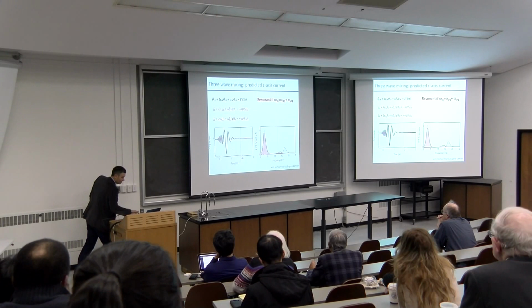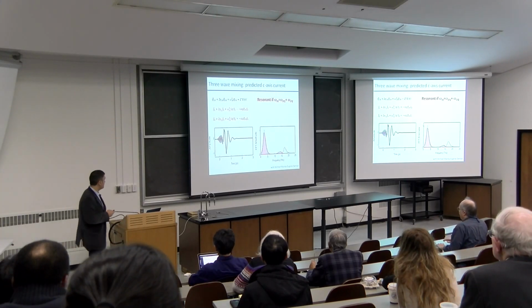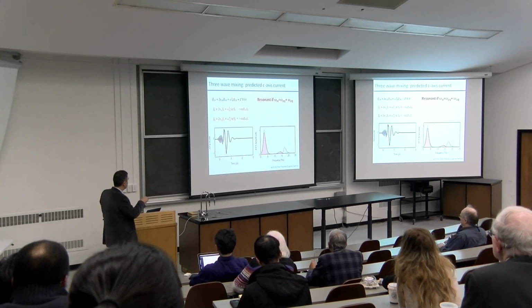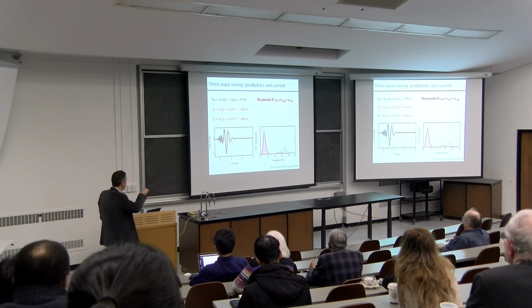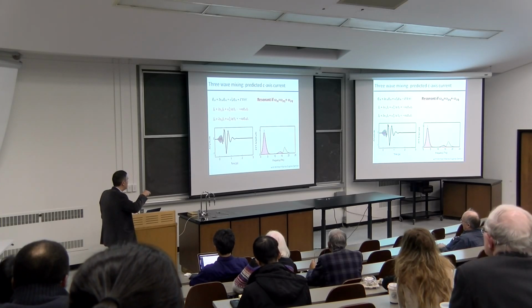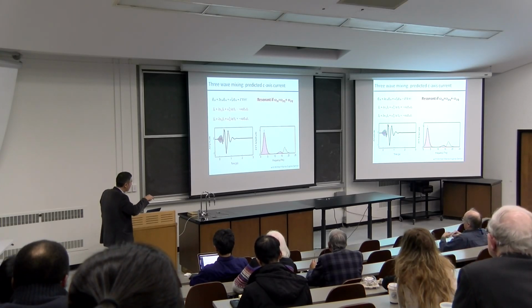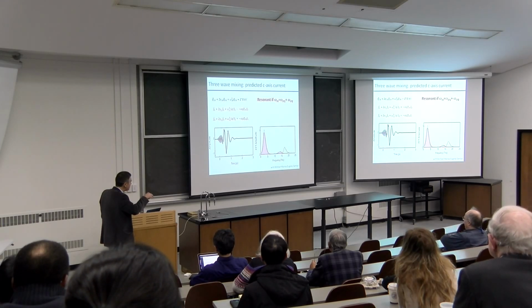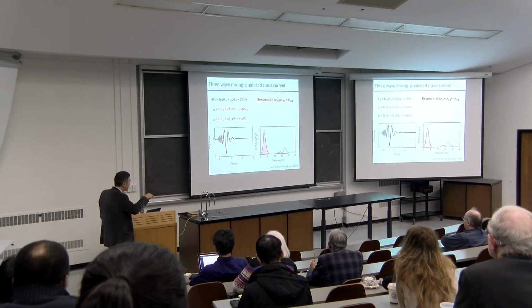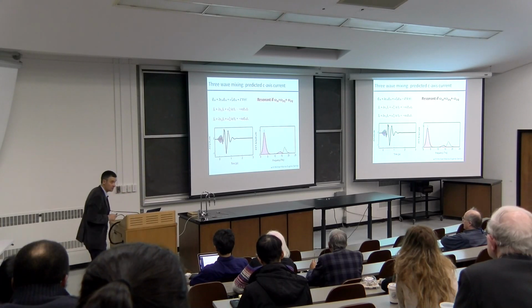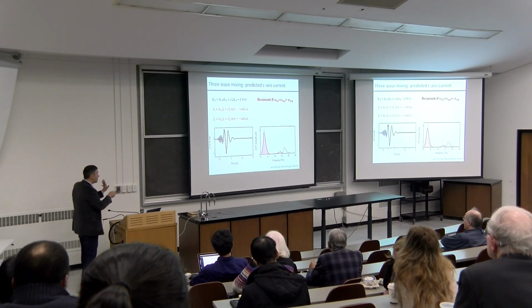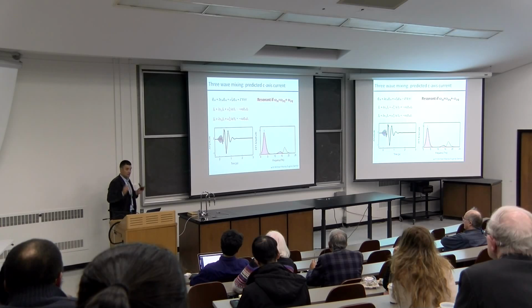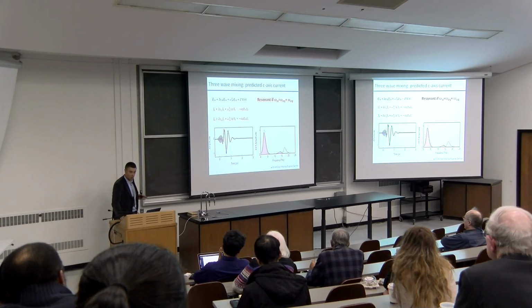And there's very specific predictions. This is now a calculation solving these three equations of motion of the current perpendicular to the planes as a function of time, where this is my driven mode, which decays into two plasma modes. This is the high frequency J2, and this is the low frequency J1. Okay? This is, again, very simple, classical three-wave mixing that one expects.